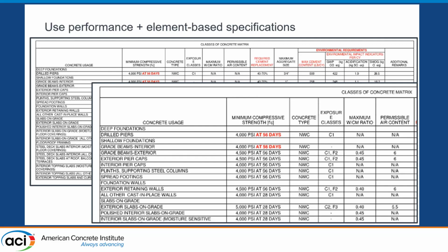What's critical here is that only what's needed is specified. For example, it's not always necessary to limit the water to cement ratio. When limiting the water to cement ratio unnecessarily, it can increase the cement and carbon footprint. So it's really important that you only put exactly what you need here and exactly what is required by code, and not more than that. We want to allow mix designers the ability to optimize the mix designs and make them as environmentally friendly as possible while remaining cost conscious. If we give them that flexibility, we will be in a much better position as a project team.